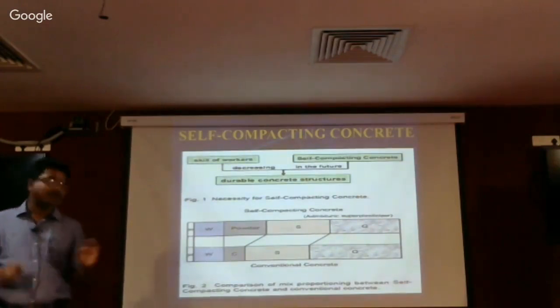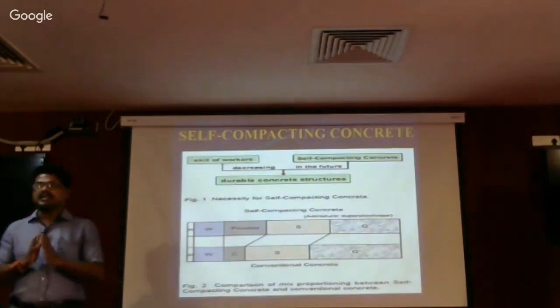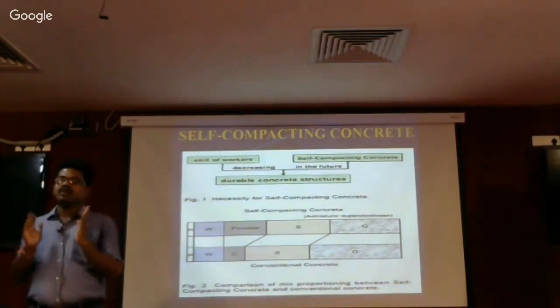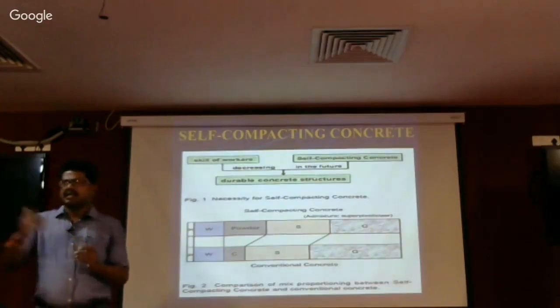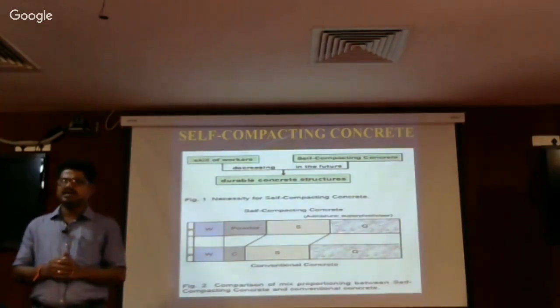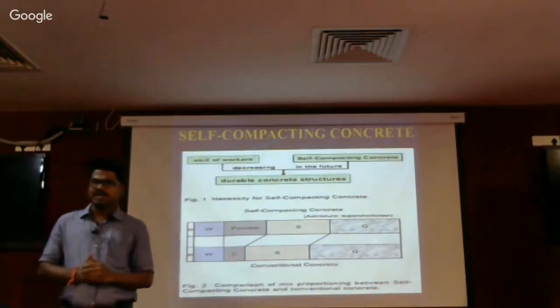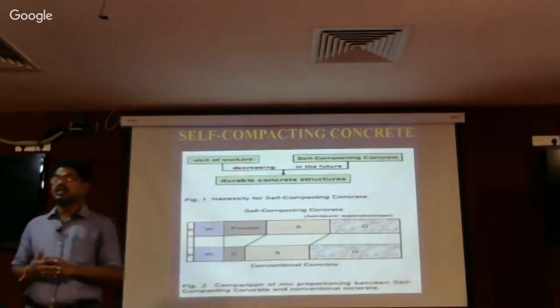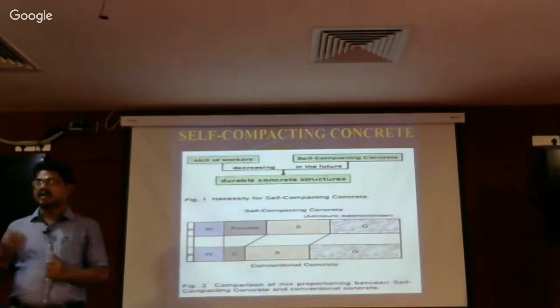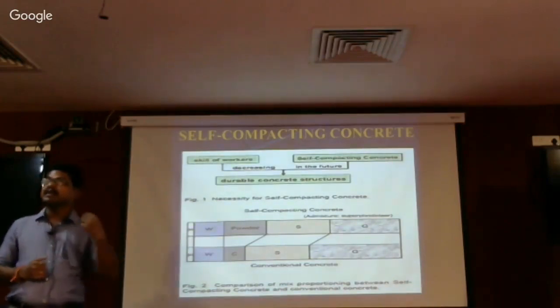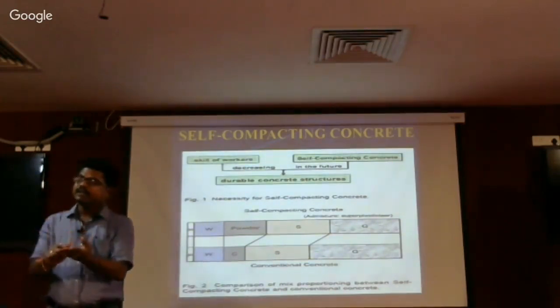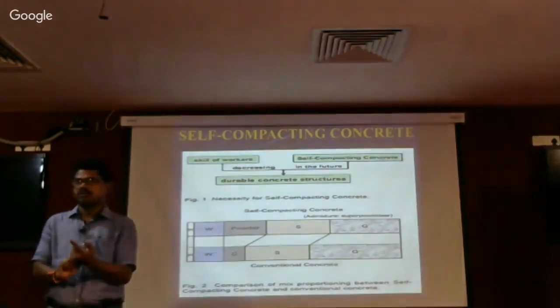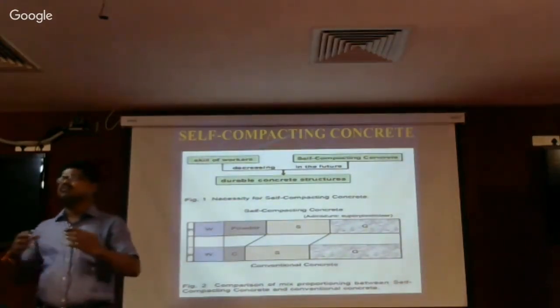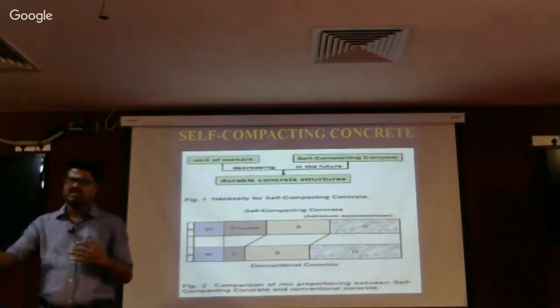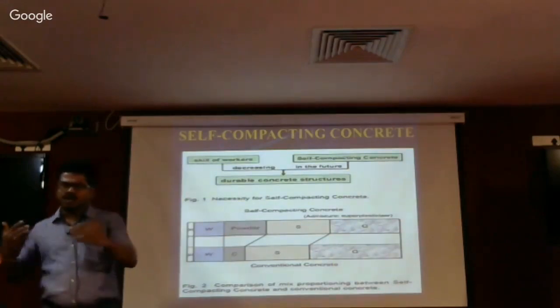Here I am saying powder, not cement, because let us say I want to develop an M30 grade concrete. Generally, with 350 kgs of cement, I can develop 30 MPa. So directly, if I am using 350 kgs, it is not economical. Here we are thinking in the direction of economy, and also in the direction of sustainability. Because if I am using more cement, more production of cement, then CO2 is coming, then environmental problems, all that we are seeing.